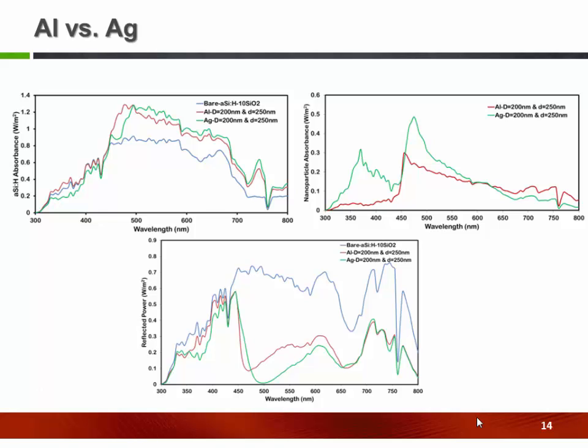To compare aluminum with silver, I investigated the absorption inside of the absorbing layer, the absorption inside of the metallic structure, and also the reflected power from the devices. As we see, we get a combination of good performance and somewhat bad performance. For example, both structures show that the absorption performance is good for both silver and aluminum, although silver has better performance for a little wider range of wavelengths.